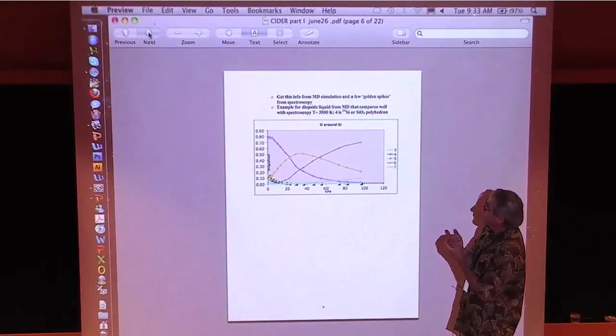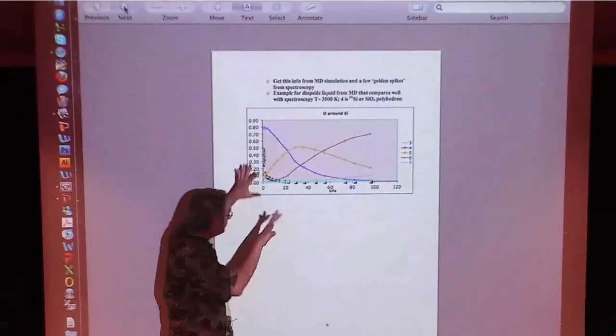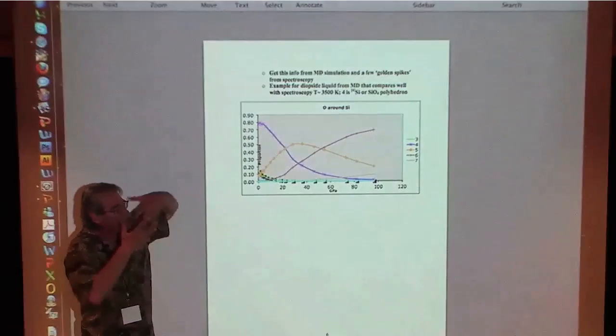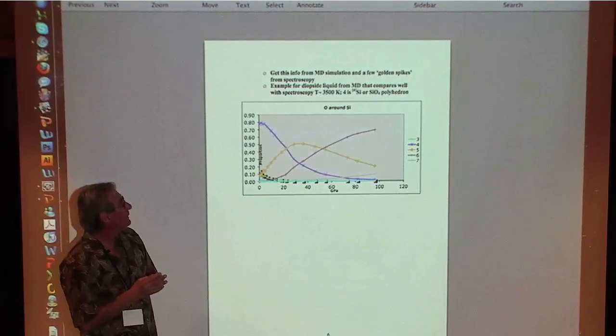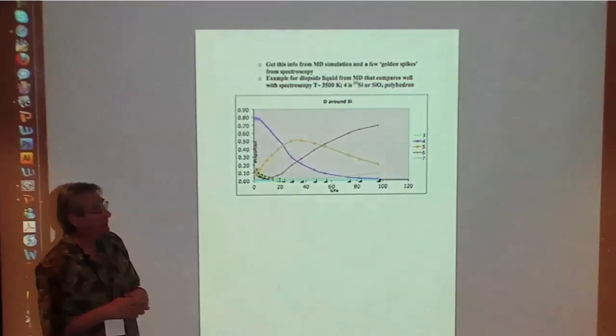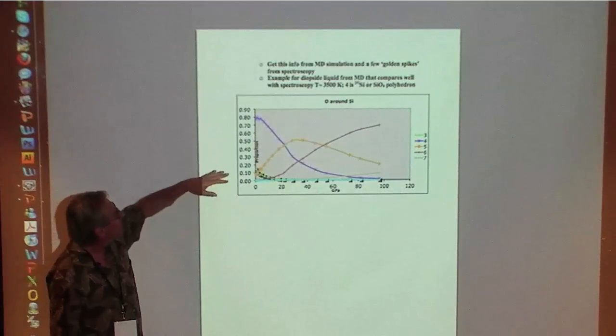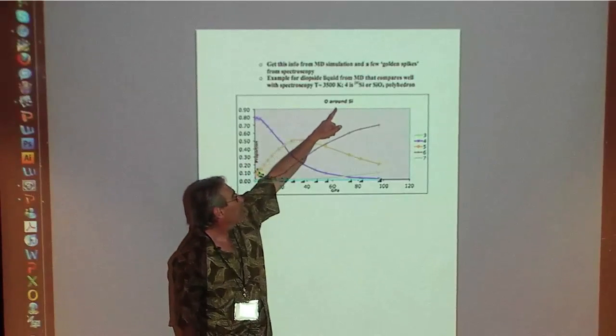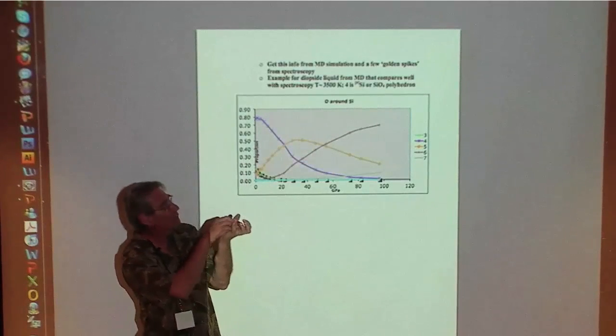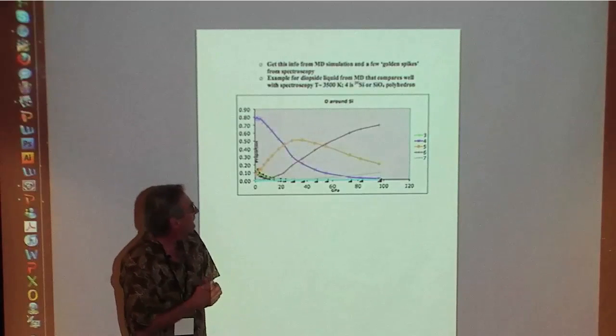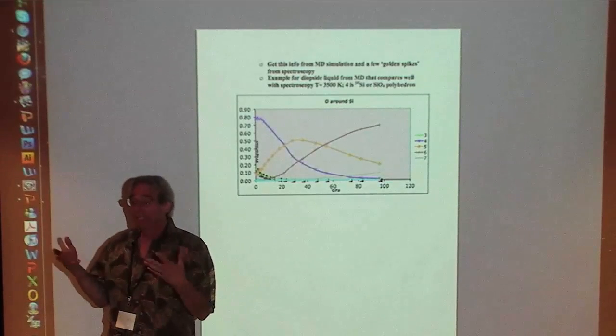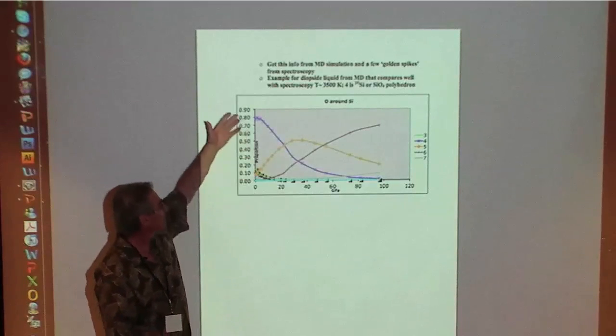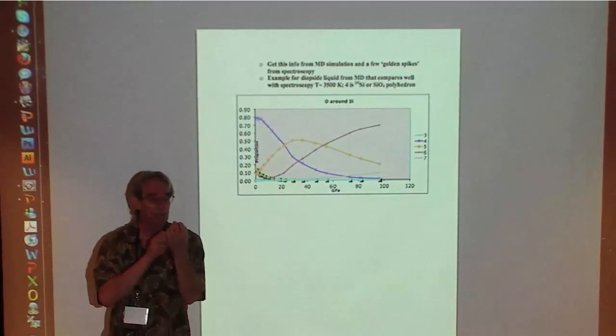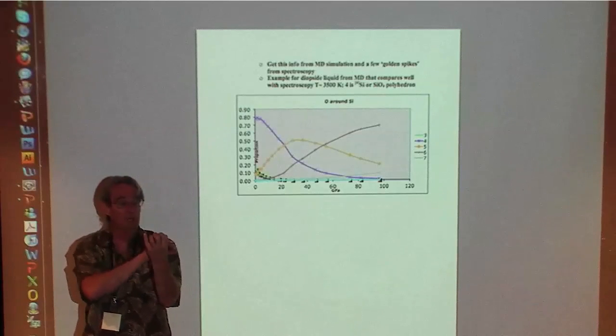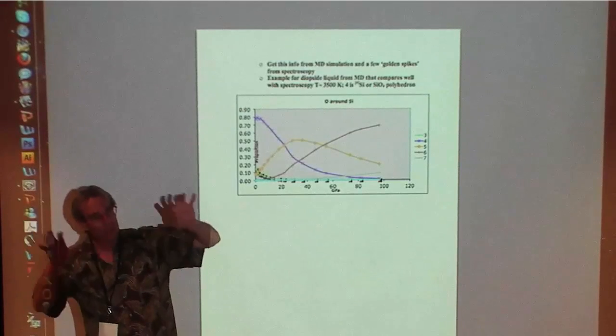So, where were we? Yeah, so speaking of molecular dynamics, this is basically here to point out that, let's think about silicon dioxide liquid, okay? When you think about it at low pressures, if you look at that liquid, you do spectroscopy, you find out about the structure, that is the oxygens around the central silicon. We all know that silicates are based on the silica tetrahedron. Right? So in crystals of silicon dioxide, all of the silicon has 4 nearest neighbors of oxygen. And then those tetrahedra are linked in a chain.